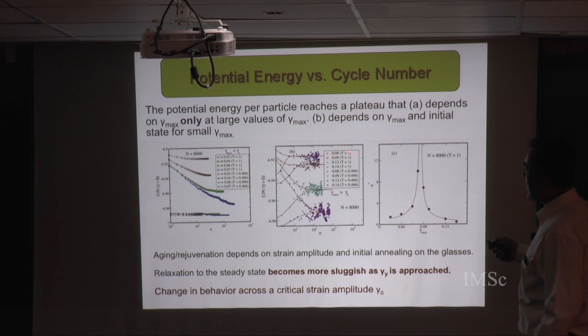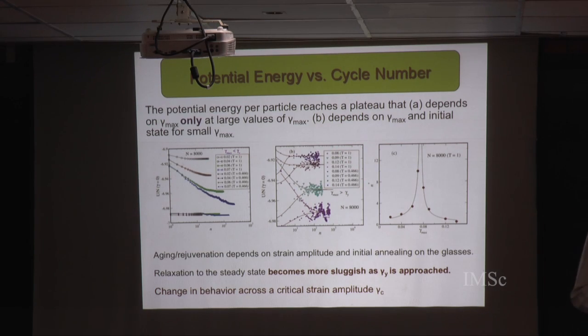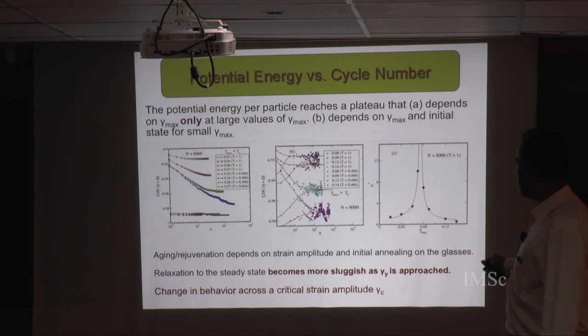On the other hand, when I apply a larger amplitude of strain, going from 0.08 to 0.14, I find that for 0.08, which is the lowest curve here, after applying a certain number of oscillatory deformations, the energies of the poorly annealed glass and the well annealed glass have both converged to a common value. This common value then remains, and this type of behavior is seen also for higher amplitudes of strain.